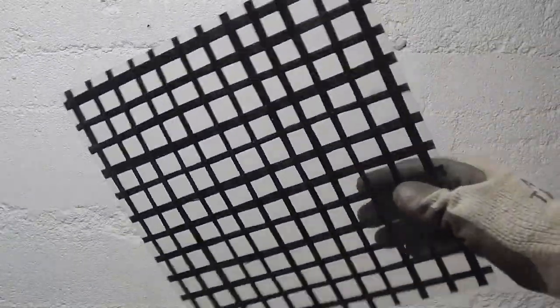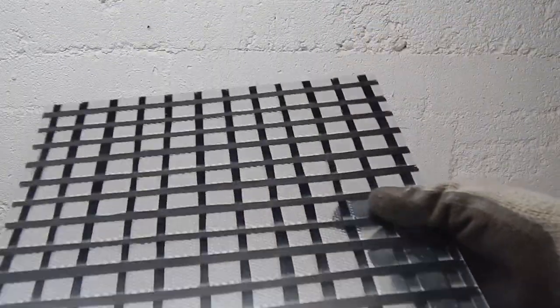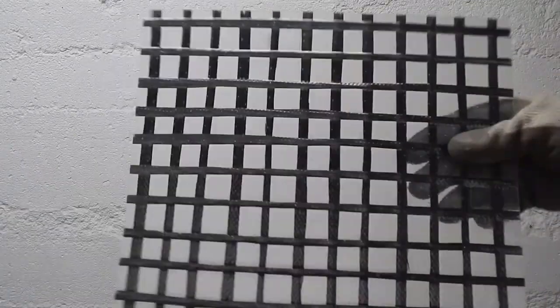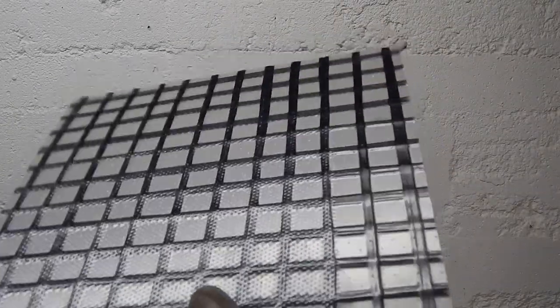Here's the finished panel. It's pretty neat stuff. It's a lot stiffer than you think it would be because the tows are actually relatively thick. You can see the asymmetry there caused it to be a little bit warped. Flow media definitely pressed in and printed where it was covering, which is not ideal.